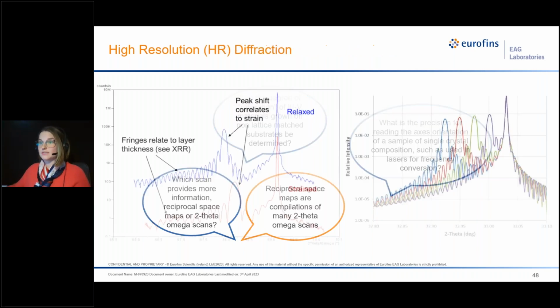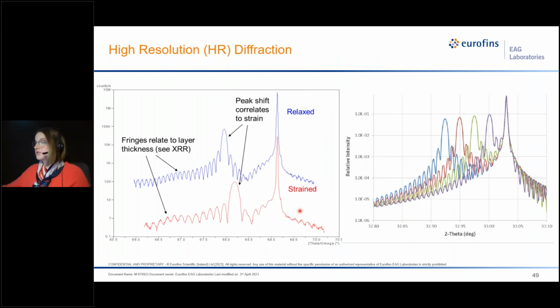So for our example today, we've got a silicon germanium thin film on the left. Now, we know that the thin films in these examples have the exact same composition, so we know that the layer peak here is shifting because of strain, not because of composition. In this case over here, we have an aluminum gallium arsenide film, and we know that the strain is the same in all these cases, but in blue we have 100% aluminum, and in purple we have 25% aluminum. So we know that the shift in this peak versus the substrate is because of composition.